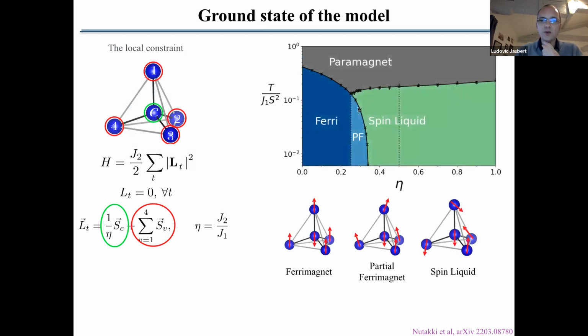Just the phase diagram that we get from classical Monte Carlo, as we move the ratio between J2 and J1, so eta is J2 over J1. As we move the ratio between 0 and 1, we go from a ferrimagnet, where the central spin is opposed to all of the other spins, to a partial ferrimagnet and to a spin liquid regime. That's what we can get exactly at zero temperature, and at finite temperature from Monte Carlo simulations.